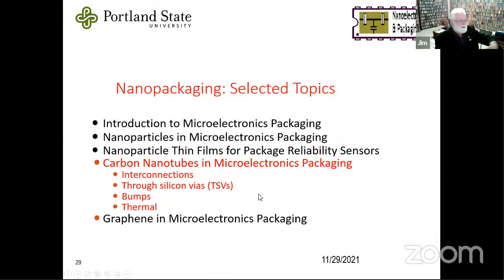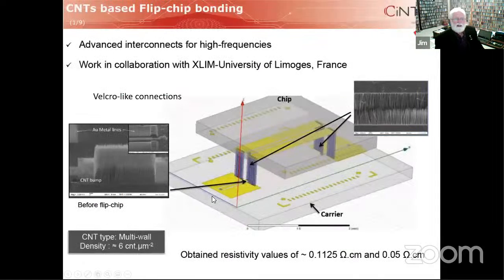So we'll move on to carbon nanotubes, mainly interconnections, but briefly thermal. And carbon nanotubes have been demonstrated here. Resistivity values of the connection ranging from around these values. But the idea here is that you grow a forest of carbon nanotubes on the chip and on the carrier, and you press them together like Velcro. And so these carbon nanotubes contact these carbon nanotubes, and you get an effect like this.